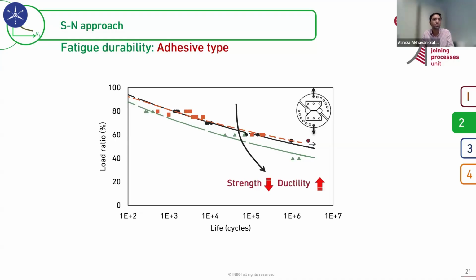But one of the important parameters, of course, is the maximum fatigue load, and this load ratio. If you are close to the static strength of the same joint, the life will be short. For example, if you are above 80% of the static strength in fatigue loading, you are very close to 1,000 cycles or something like that. If you are at 50%, you are between 100 thousand and 1 million. If you are loading lower than 50%, the life can be over 1 million cycles, if you keep the other parameters the same.